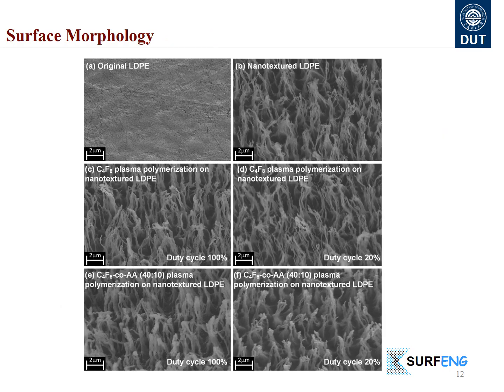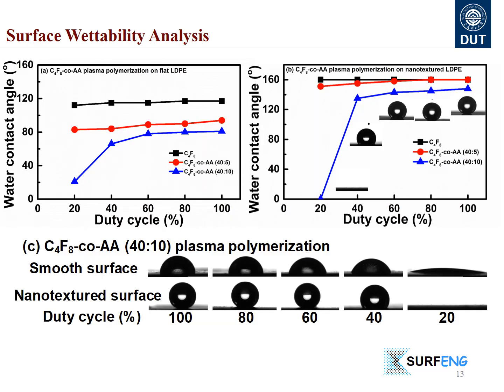It is a renowned fact that the correlation of surface chemical composition and surface morphology determines the surface wettability. A series of FeSEM micrographs are shown in this slide. The hydrophilic carboxylic acid group controls the wetting state and the hydrophobic fluorocarbon group controls the dewetting state, as the presence of polar carboxylic acid group allows polar water to penetrate into plasma copolymer coatings, and the presence of nonpolar groups like CF2 and CF3 of low surface energy repel water. The surface wettability changes from superhydrophobic to superhydrophilic by lowering the duty cycle.